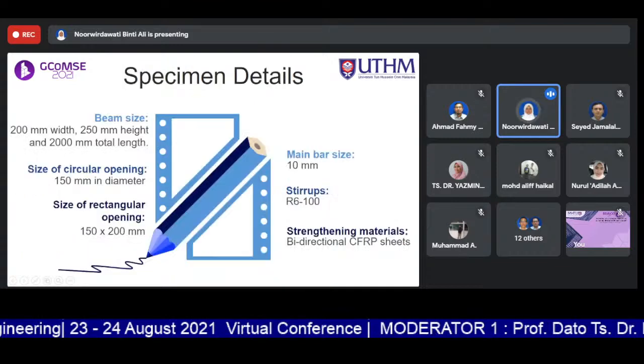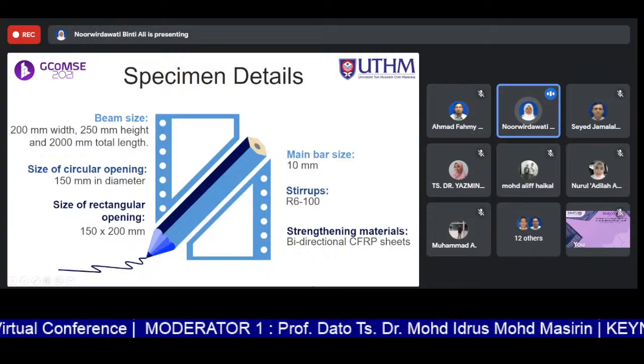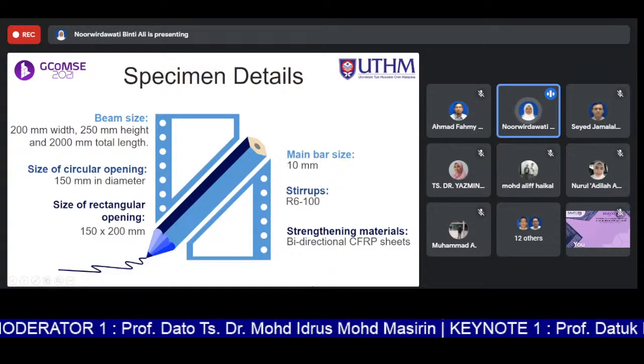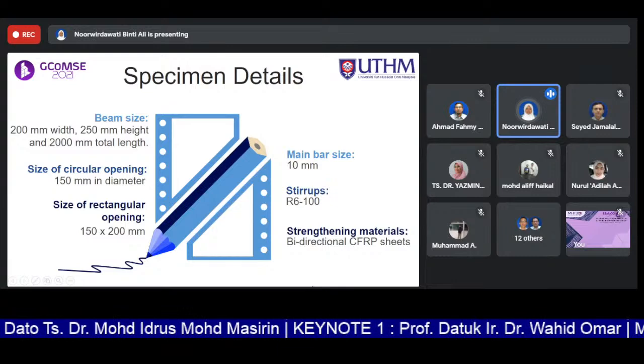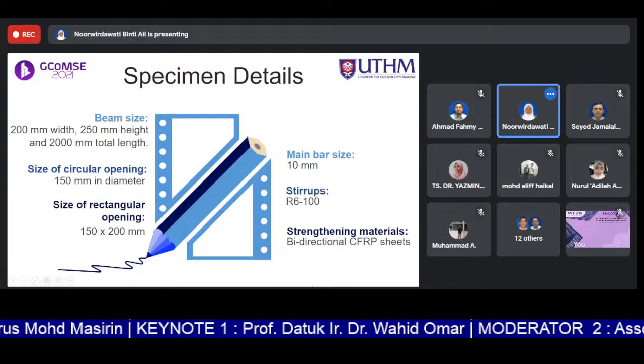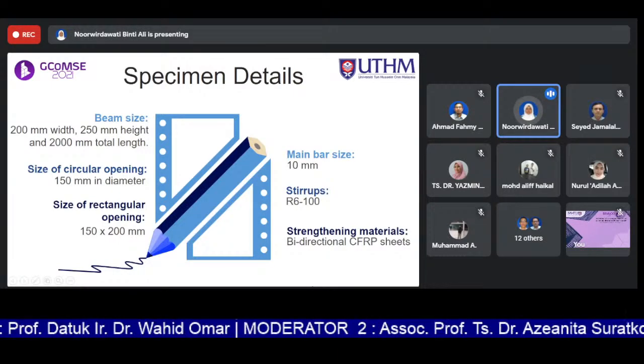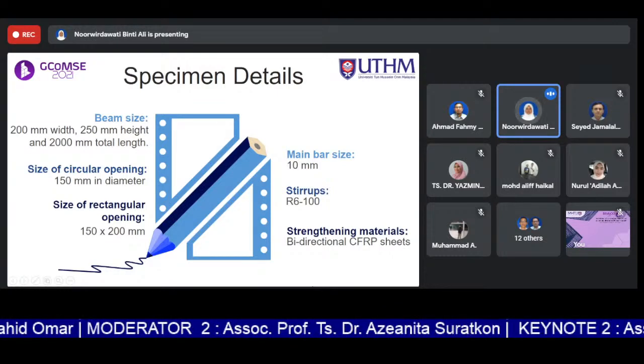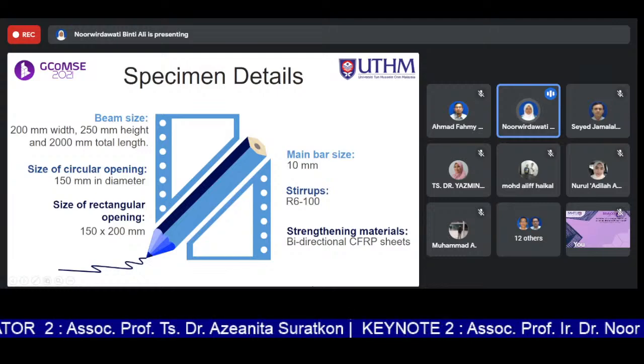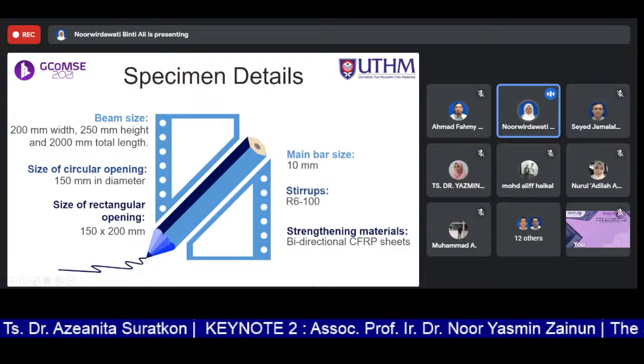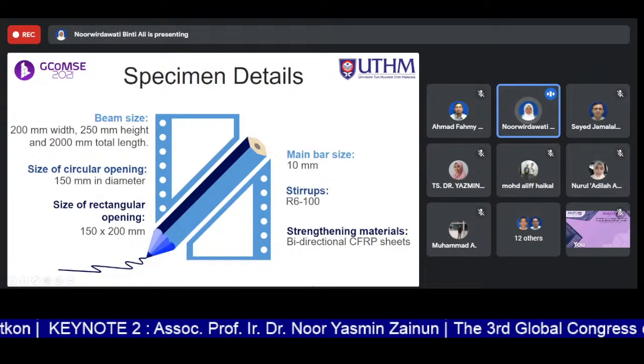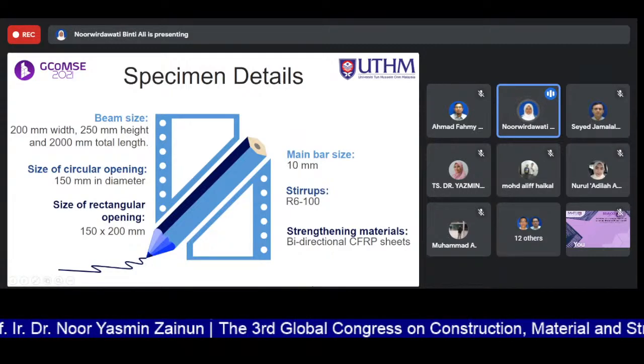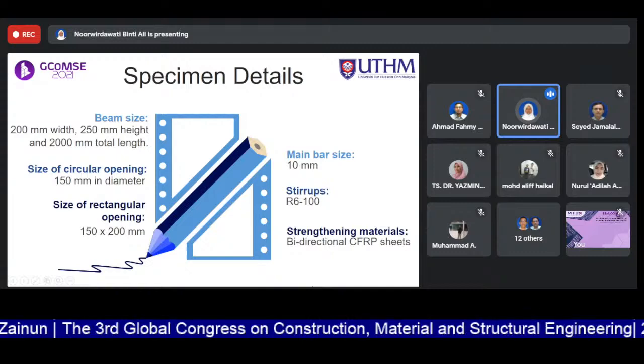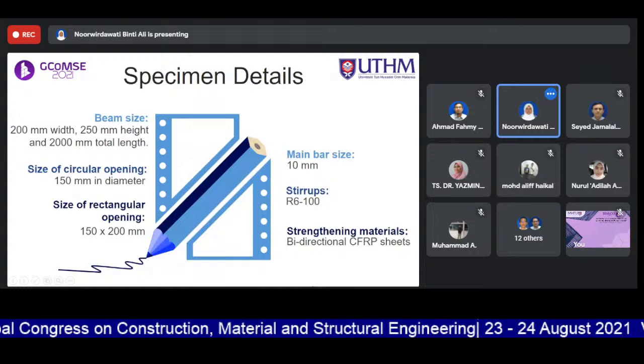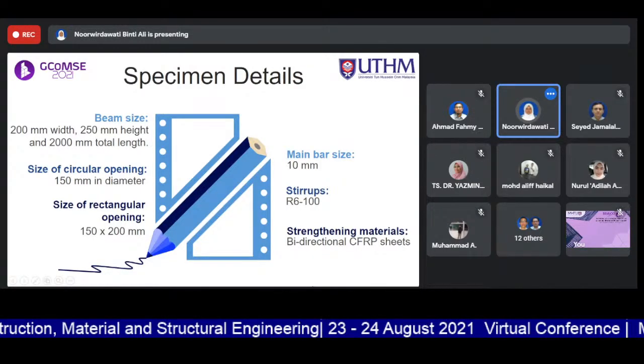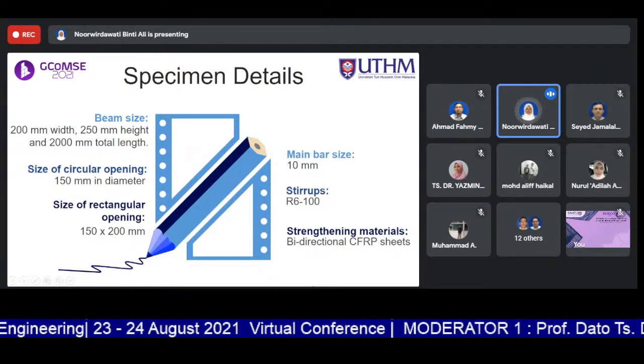So the specimen details: the size of the beams is 200 mm width and 250 mm height with 2000 mm total length. This brings the effective length of the beam to 1700. The size of the circular opening is 150 mm in diameter, while the size of the rectangular opening is 150 times 200 mm. The size of the main bar is only 10 mm because we designed the beam to fail in flexure. Because we want to study the flexural capacity, we want to make sure the beam fails in flexure so that we can study the flexural enhancement capacity. And the stirrup used is R6 at 100 spacing. And the strengthening material used is bidirectional CFRP sheets.